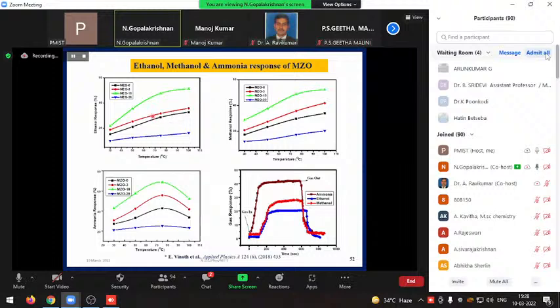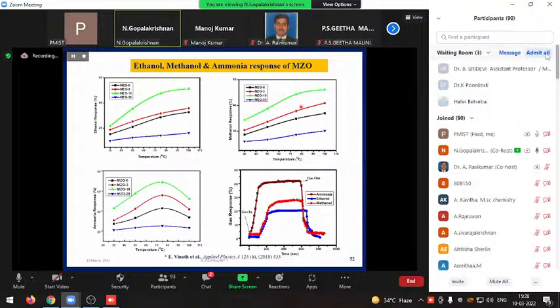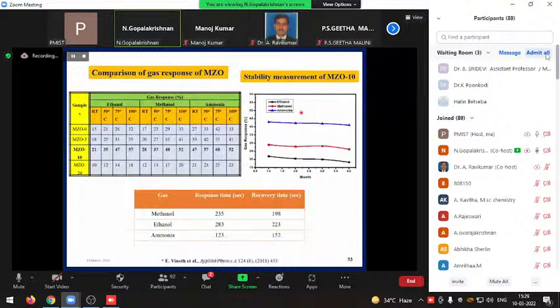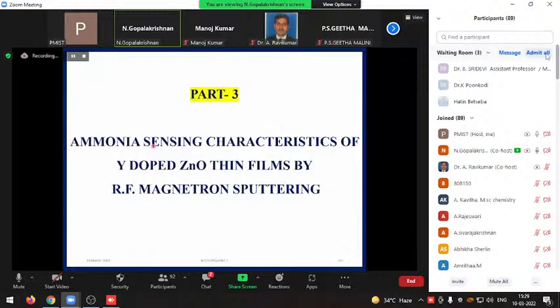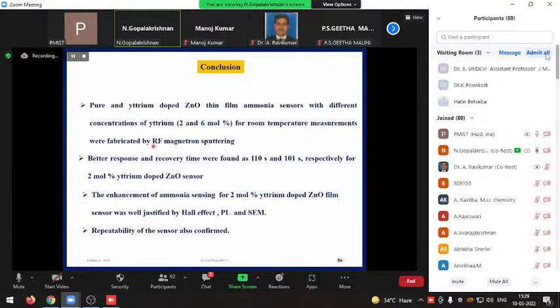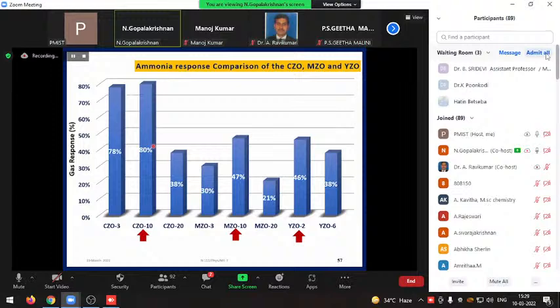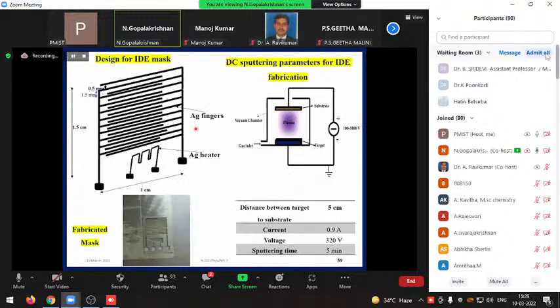For the first two cases, the sensing efficiency increases, and in the third case the sensing efficiency decreases. However, we get enhanced efficiency upon doping with magnesium. Again, we measured the response and recovery time, and we made some bar charts here.